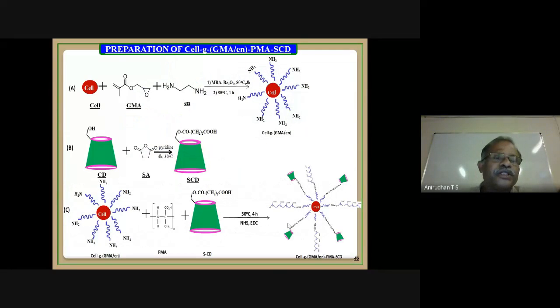Here we also used cellulose, then GMA and ethylenediamine treatment, and we have introduced an NH2 group in cellulose. Remember that cellulose is associated with only primary alcoholic OH groups. Then in another step, cyclodextrin reacts with succinic anhydride. We have introduced a COOH group in cyclodextrin, and it reacts with the earlier product, and we have a material with hundreds and hundreds of alcoholic OH groups and COOH groups. This material is utilized to bind non-covalently with